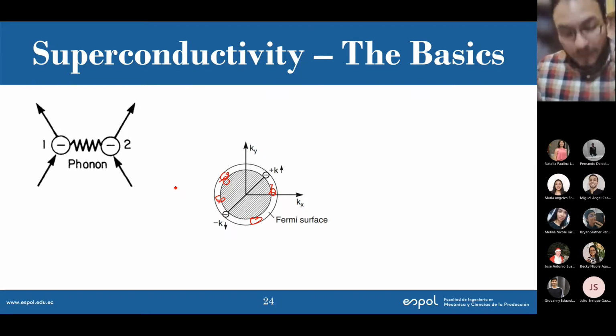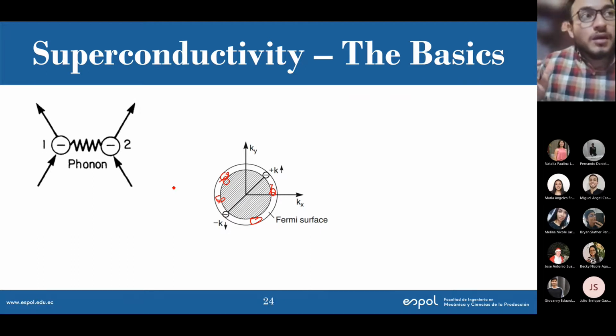That's why, if you think about it, poor conductors in the normal state are potential candidates, and that's why ceramics are like that. Poor conductors in the normal state are nice candidates for superconductivity at low temperatures. Whereas very good conductors, that's why copper is not a superconductor. Very good conductors in the normal state are not candidates for superconductivity. You don't see superconductivity in copper, for example. You see superconductivity in ceramics, which in the normal state are usually not good conductors.